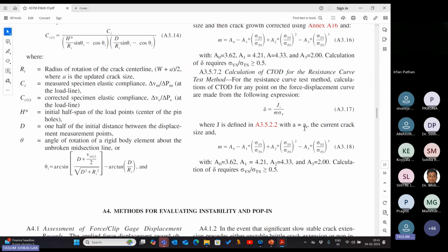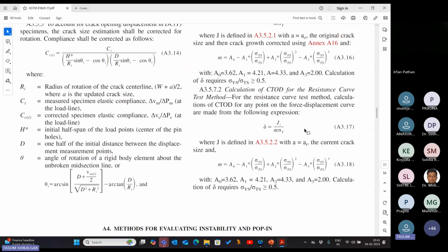So in a similar way, I developed correlations for PSPT specimens. Now ASTM has also referred to my papers, but they are testing this type of correlation for multiple materials. They want to know, is it valid for all materials? If it is not valid for all materials, then they will find the polynomial constants for each material.